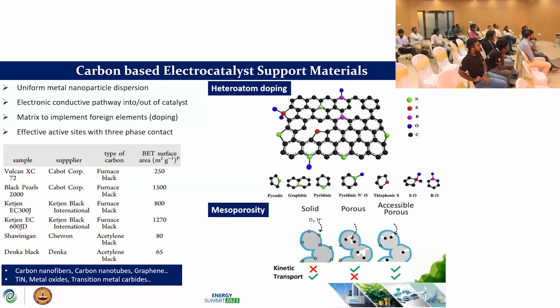One way to improve the properties is to dope some foreign elements like nitrogen, sulfur, boron, or phosphorus. This kind of heteroatom doping will aid in improving the properties of the support material, especially the durability as well as the uniform deposition of the electrocatalyst. It will also improve the active sites with the three-phase boundaries. There are many carbon-based support materials that are already commercialized, like Vulcan carbon and Ketjen black. In India nowadays we are trying to use these commercial carbon-based support materials, but of course their properties have to be improved further.